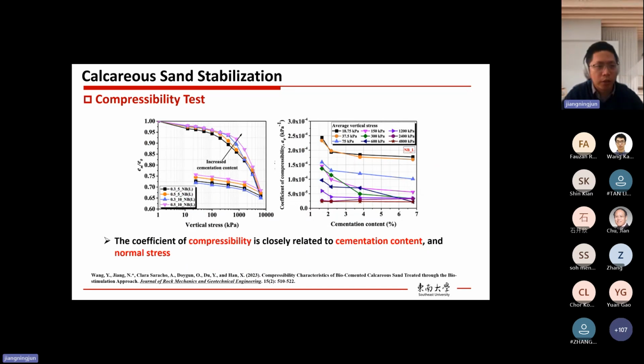Then the one-dimensional compressibility test also shows a similar trend. With increased cementation content, we can see the compression curve shifts upward. So it means that the soil's ability to resist compression has been improved. Then we calculated the coefficient of compressibility, a_v, at different stress ranges. Similar to the direct shear test results, with the increase in cementation content, the coefficient of compressibility a_v drops. So it means that MICP helps to reduce compression. And then, at high normal stress conditions, this improvement by MICP becomes diminishing. I think the mechanism is similar to what I explained for the direct shear test.